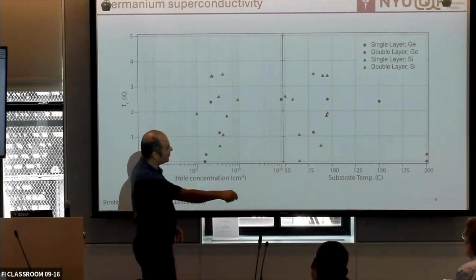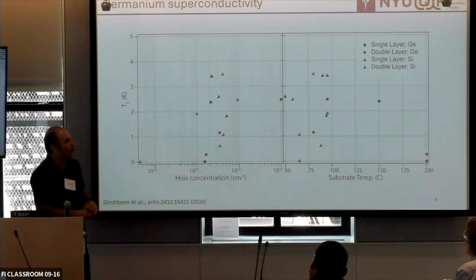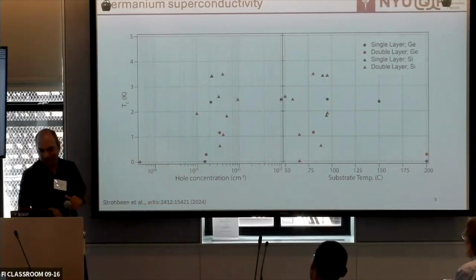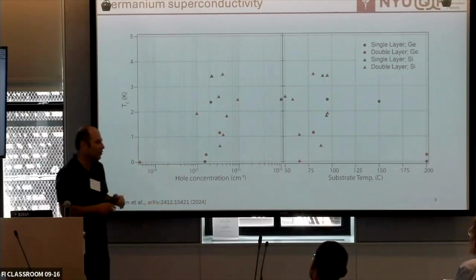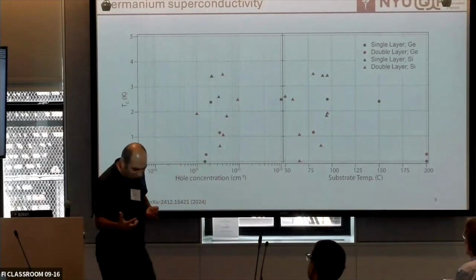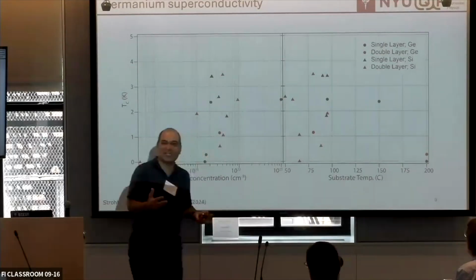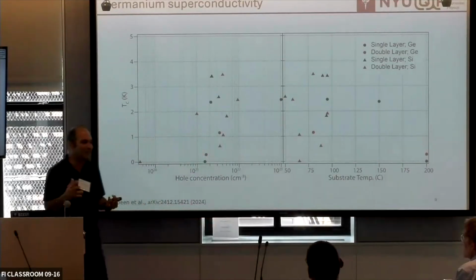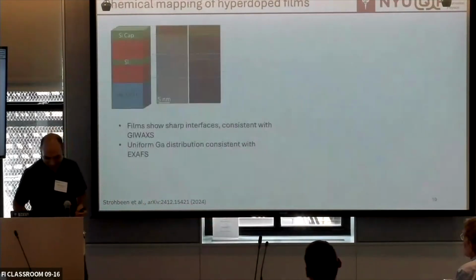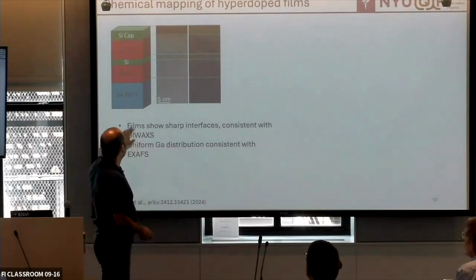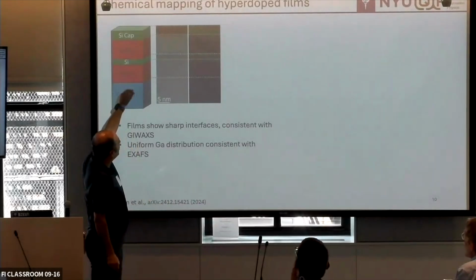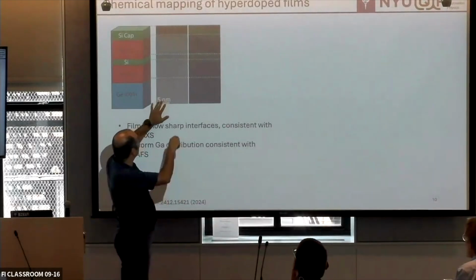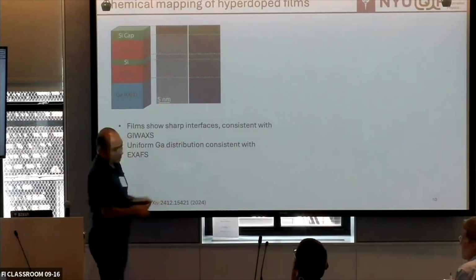We changed the substrate temperature, trying to get the stability of all of these single layer, double layer, triple layer, everything superconducting. So we were happy. So we achieved a very high density. Now the question is, is it clean, right? Or was it a mess like the other one I showed you, right? So this is a cross-sectional TEM of this double layer. You already see that it actually looks pretty clean.